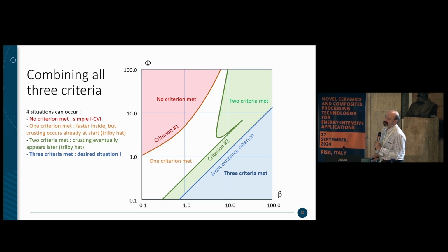And this is what I call the Trilby hat effect, okay? Because you have a profile like this. And the second criterion here is that what we want is that really the distribution of the reaction rate does not display an extremum inside the material. And the last criterion is the existence of an infiltration front, which is simply a standing wave that goes from the inside to the outside and infiltrating nicely the whole material at its best efficiency.